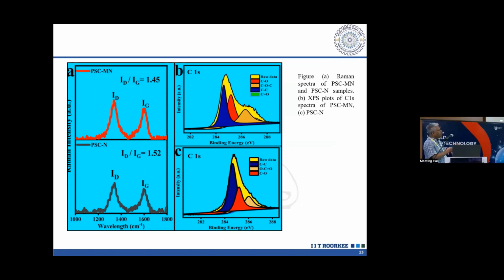And then this XPS analysis shows what surface groups are present, like carbon-carbon, which is due to disordered carbon, and carbon-oxygen groups present, because the presence of oxygen on the surface may trap the sodium, and then the sodium will not be able to penetrate inside the structure, and it will change the capacity of the material. So this is where all these studies were required, and this was conducted.